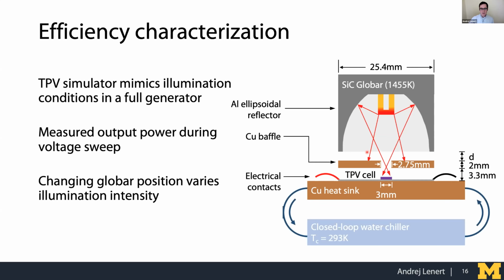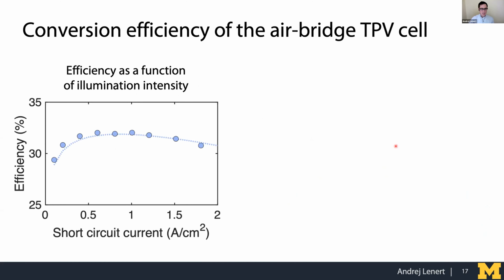So to do this, we developed basically a TPV simulator setup, sort of analogous to a solar simulator setup. But here we're using a Globar source at about 1450 Kelvin. And we can vary the illumination levels by changing the distance relative to the TPV cell. And what we see is that as we increase the illumination level and consequently the short circuit current, voltage gains up to some point at which ohmic losses begin to dominate, and then we see plateauing and even a downturn in efficiency.